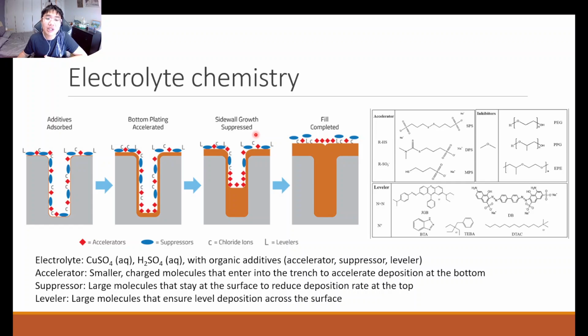Right? Why is this so? This is because without the suppressor, the deposition rate at the surface will occur at a much higher rate, because the diffusion of Cu2+ ions to the surface of the wafer is going to happen at a much faster rate than at the bottom of your trench. Because at the bottom of the trench, it's harder for mass transport to occur. You can think of the diffusion layer to be much thicker, more than the entire height of your trench. And so that's why we need these suppressors, to balance out the deposition rate, to allow the deposition rate at the surface to be slower, such that the deposition rate in the trench and vias can catch up.